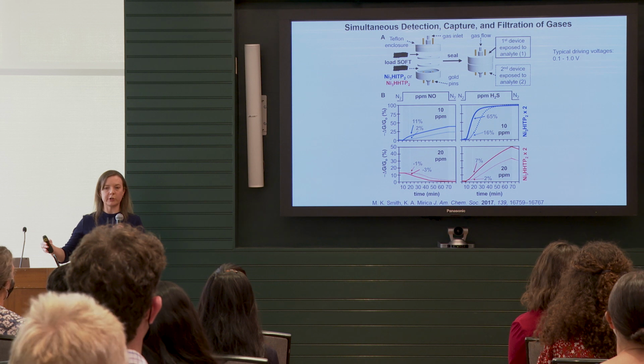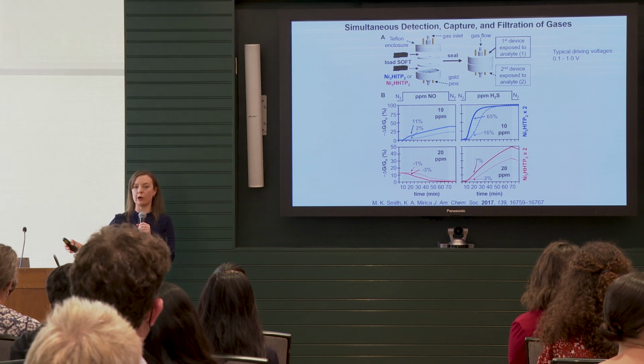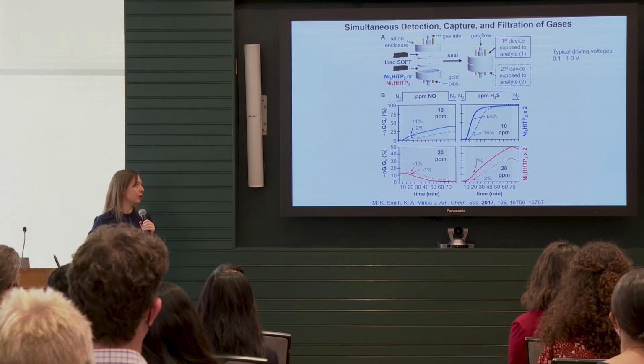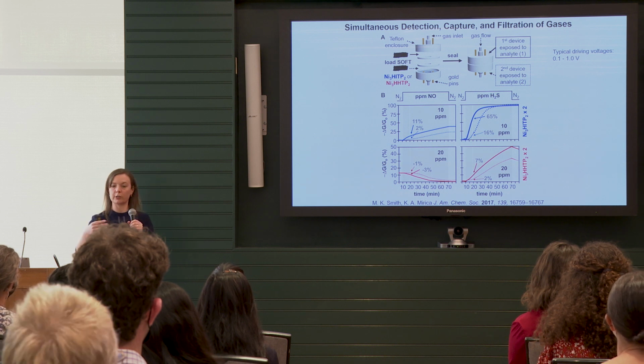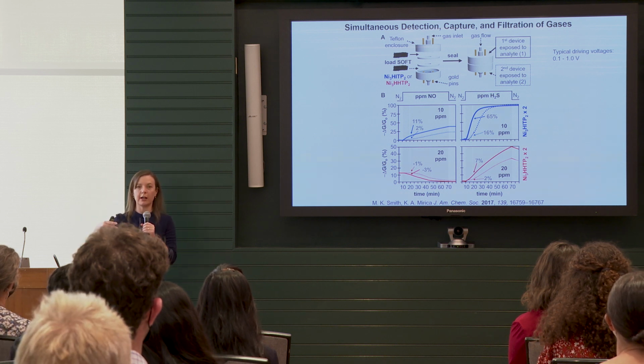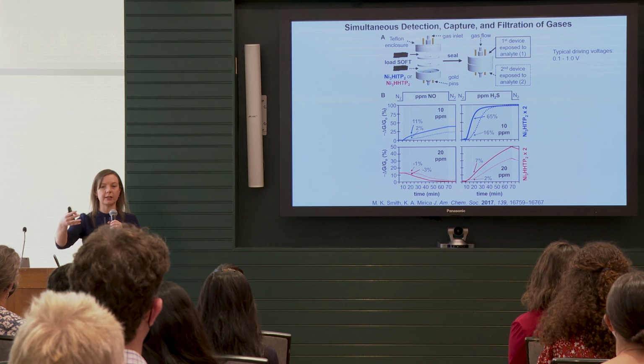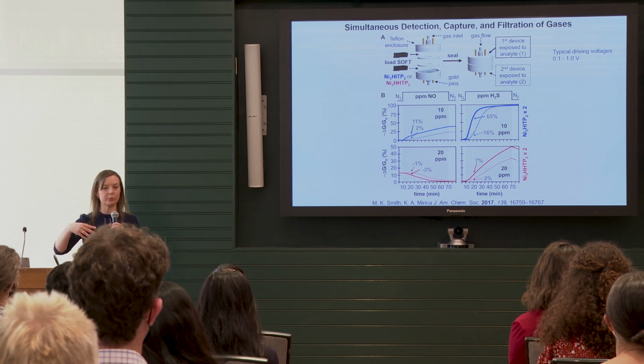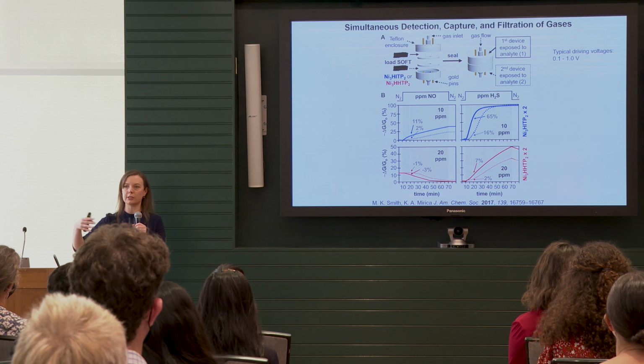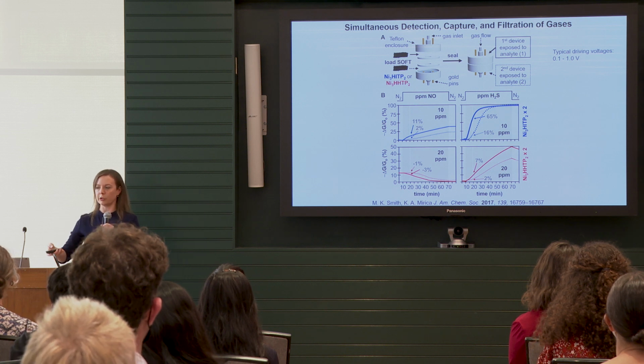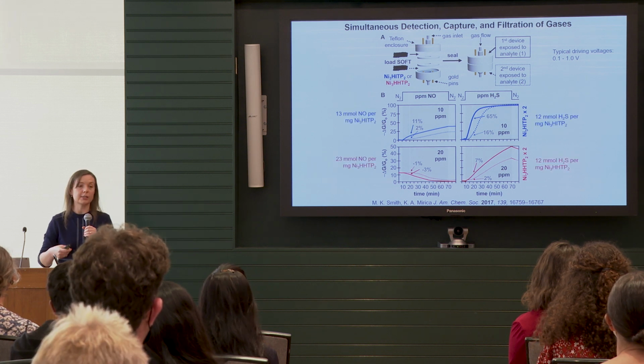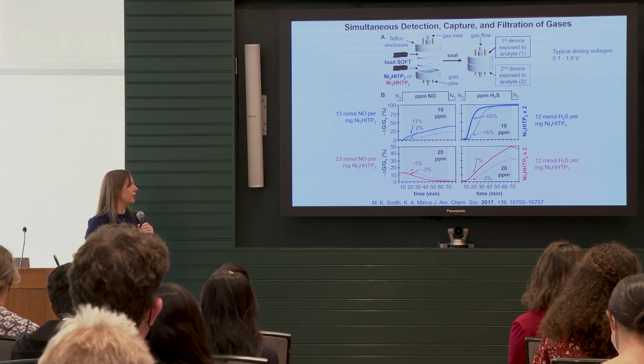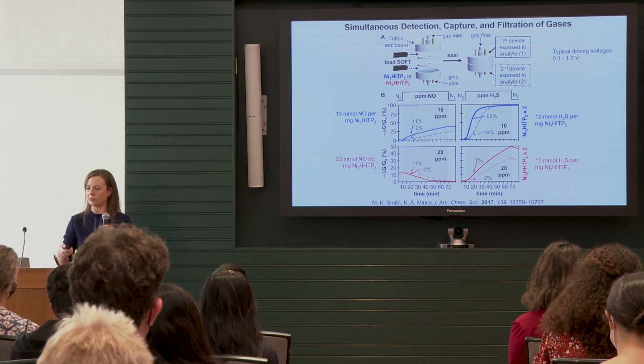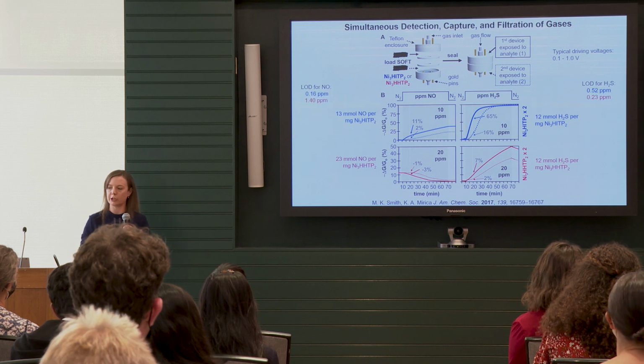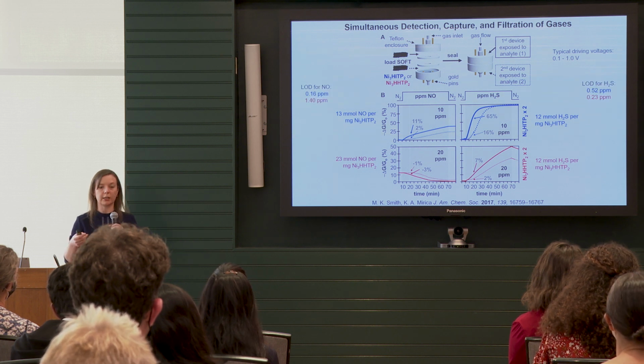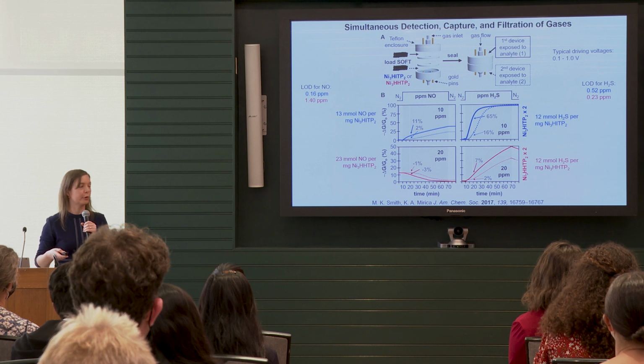But the onset of the response to the second sensor is slowed down by the presence of the first. And this is because we have a dosimetric response, so the sensors don't recover. They act as dosimeters due to the fact that the gas is being taken up into this porous material and does not come through until some kind of breakthrough capacity has been reached. From that, we can estimate an uptake capacity for these devices to be in the 10 to 20 millimoles per milligram of the material, and still maintain the limits of detection in the low part per million regime.